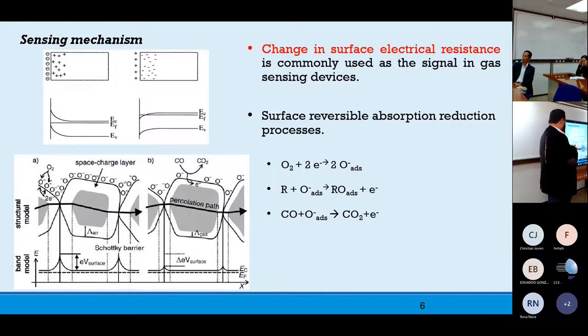The oxygen is absorbed on the surface of the semiconductor, as you can see in the figure in the letter A. And this oxygen can react with the carbon monoxide as a reductant gas. This reductant gas reacts to convert into carbon dioxide and to set free electrons. That means that the resistance of the surface of the semiconductor is going to decrease. And we can measure that change in the electrical resistance on the surface of the semiconductor.